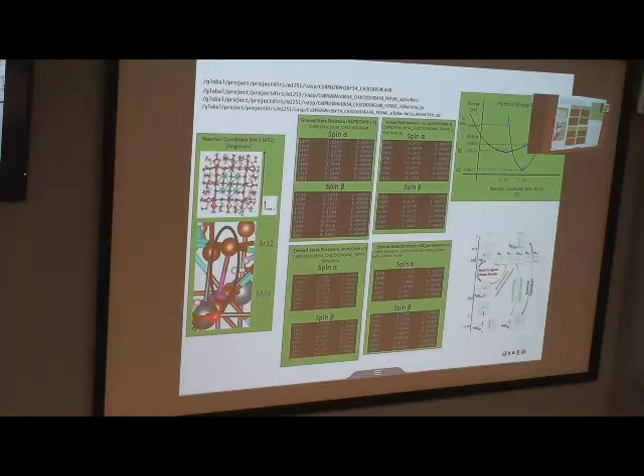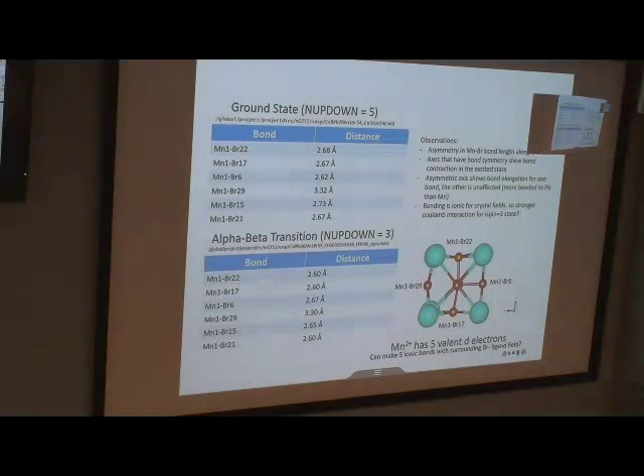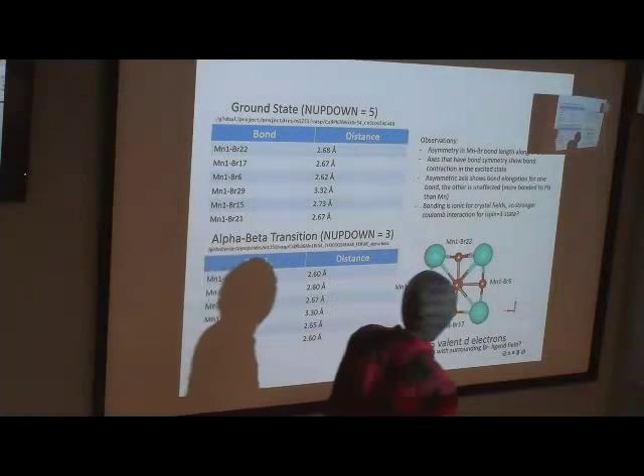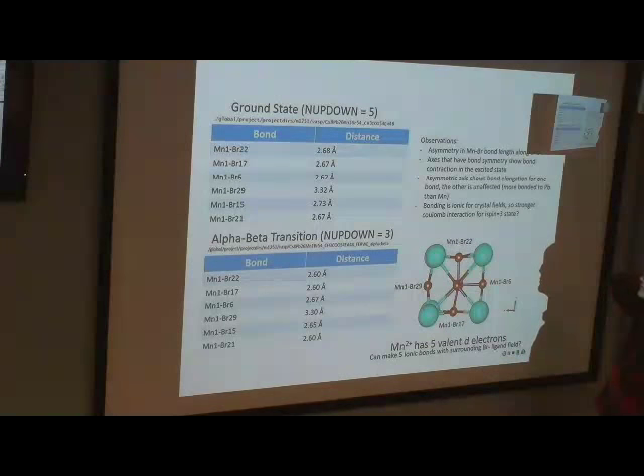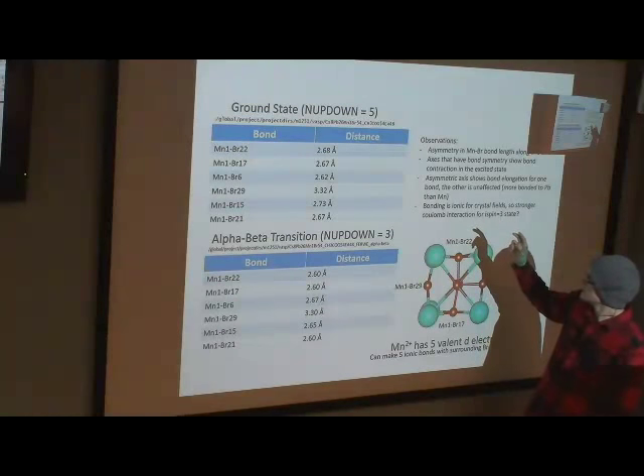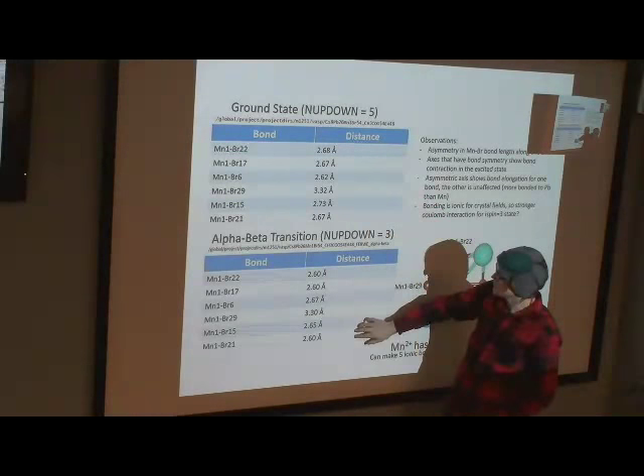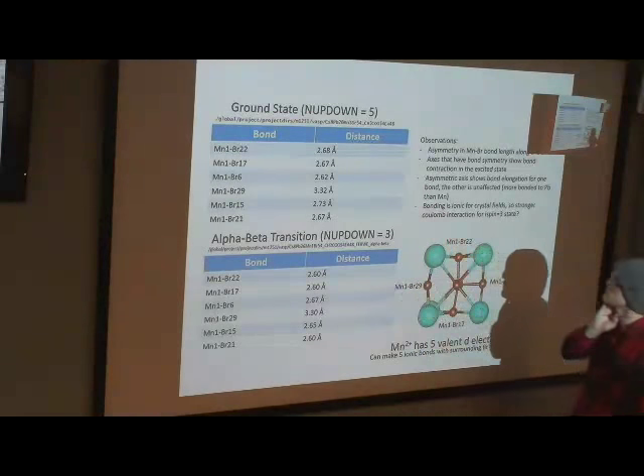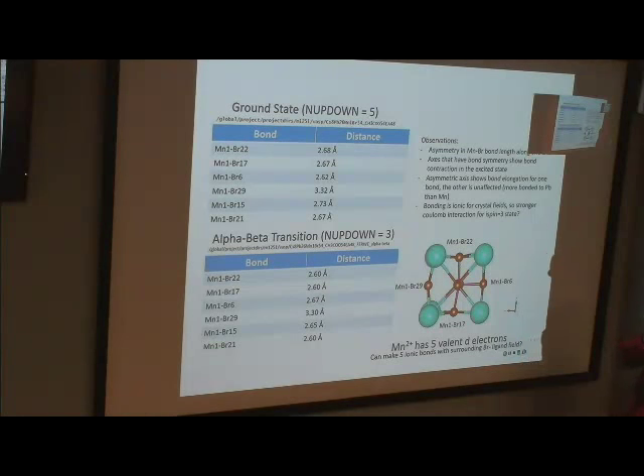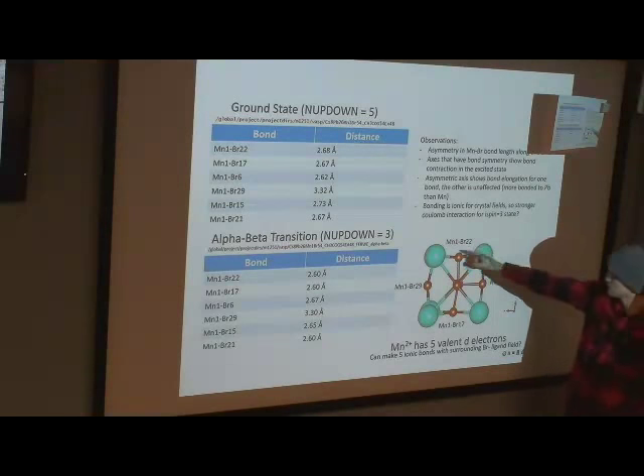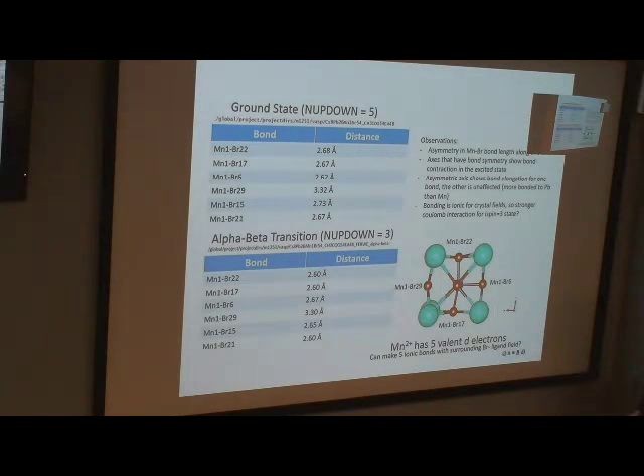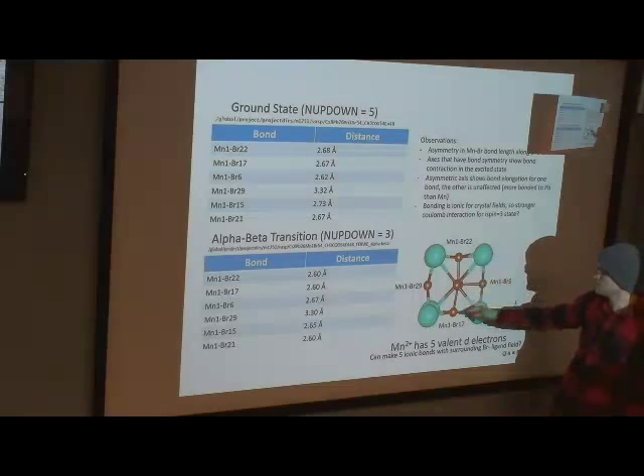I thought that was kind of an interesting finding. So then I looked at all of the surrounding bond distances in the system, and I made a table of the ground state bond lengths and the bond lengths in the excited state. You can see that for 4 of them there's a bond contraction, and for 2 of them it either elongates or doesn't really change at all. Looking at the local environment of the dopant, the 4 bonds that contract are symmetric with each other around this axis here. So these are all the 4 bonds that contract.